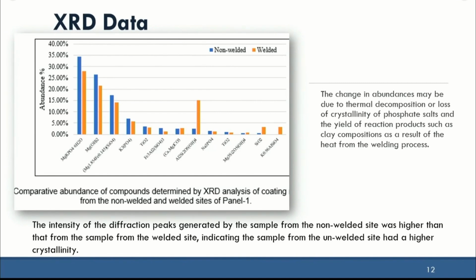What we found: the blue one is the non-welded, and the orange one is the welded sample. We took samples from welded, and we took samples from non-welded, just a coated panel that did not have any heat effect. What we found is that the heat of the welding decreases the abundance of the crystalline product and increases the abundance of the amorphous product. So it has some changes in the morphology of the coating.